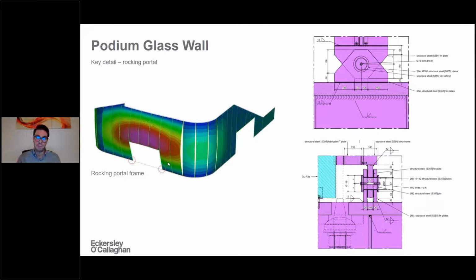With the rocking portal frame, providing a pin at the base of the portal frame, we tried to allow the portal frame to follow much more the deflection of the glass and the rods. Therefore, the portal frame is not independent out of plane because it's not stable, and therefore needs to be restrained back on the side to the adjacent rods.